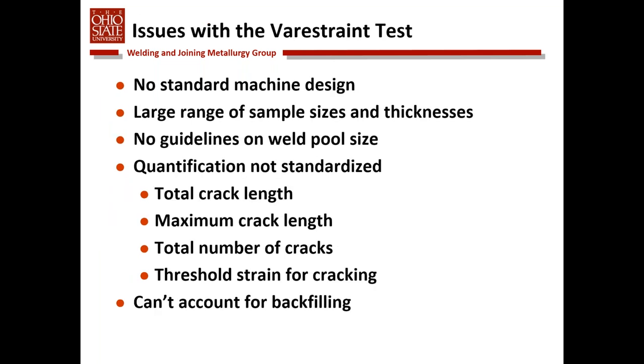So there are some issues with the Varestraint test. There's no standard machine design. Everybody who has a Varestraint machine has built their own to their own specification. There's a lot of different sample sizes and thicknesses. There are no guidelines on the weld pool size. So, how big is the weld pool? The bigger the weld pool, the higher the heat input, the higher the tendency for cracking. And so there needs to be some guidelines there. The quantification method is not standardized. These are the things that people typically use.